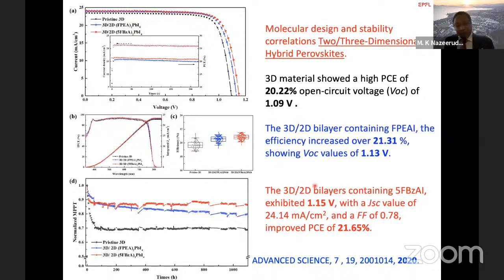So this shows the beauty of tuning the two-dimensional perovskite cations. And the reason why we have taken the pentafluoro is that they are hydrophobic. So perovskites are hydrophilic material. So you have two functionalities incorporated into this material. One, surface passivation. The second, its hydrophobicity protects your perovskite. Now, if you look at the stability data measured over 1,000 hours with the pentafluorobenzylamine, the stability is greatly enhanced.